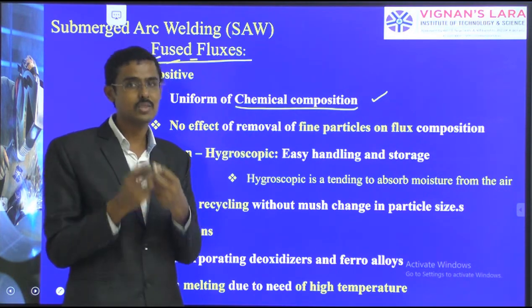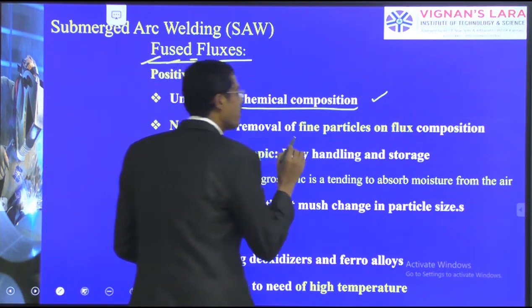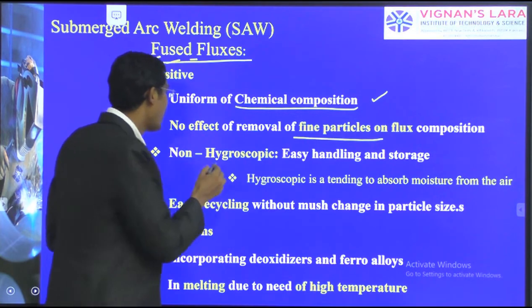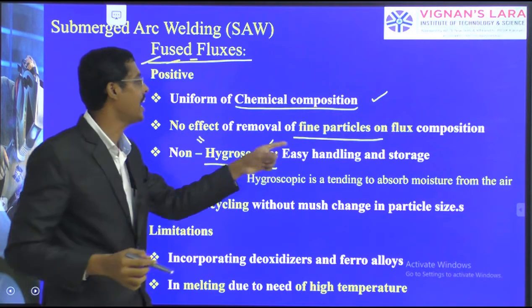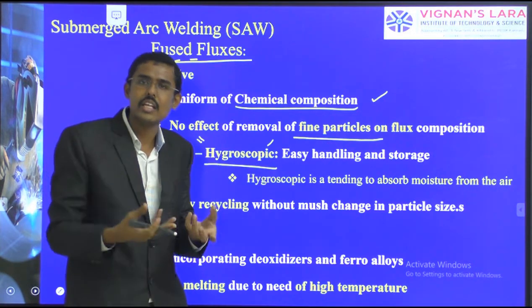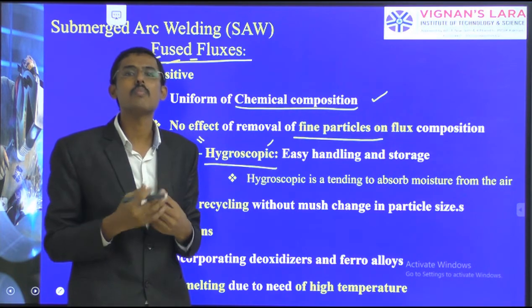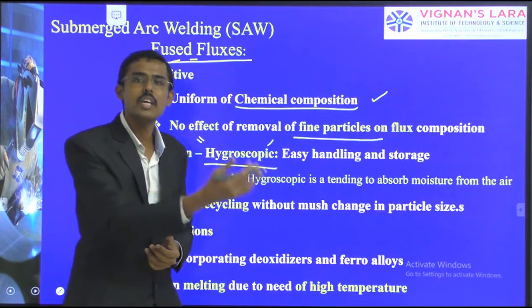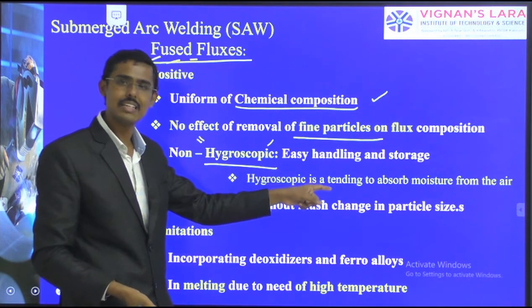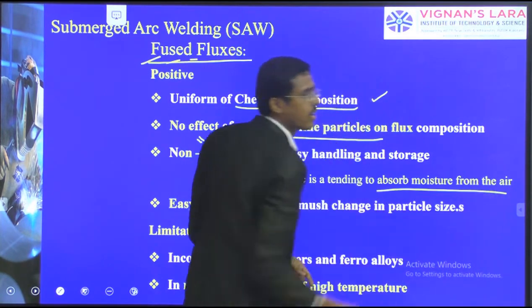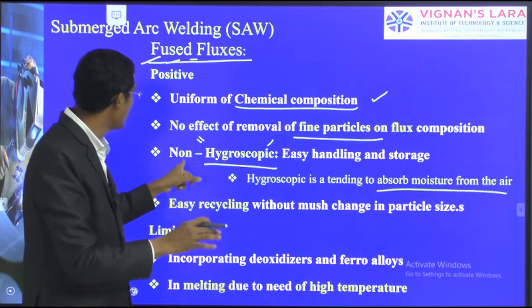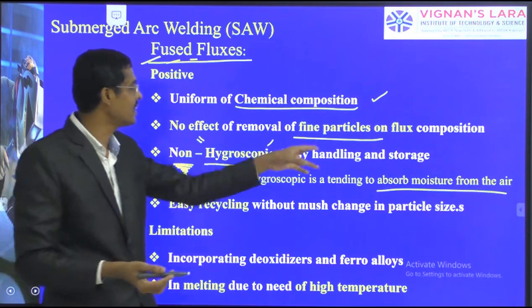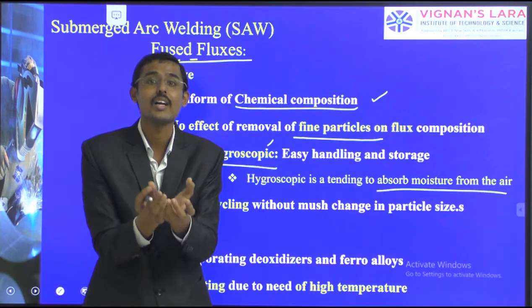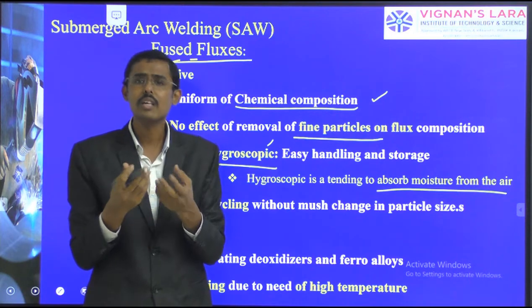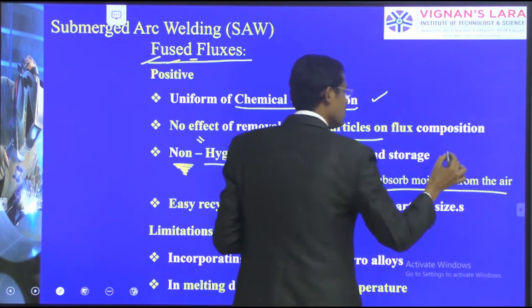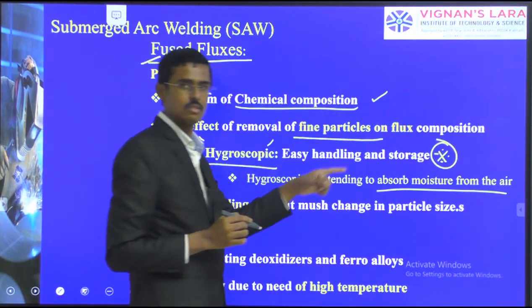Uniform chemical composition is good for the mechanical properties. There is no effect of removal of fine particles on the flux composition. Now, hygroscopic: this word is very important. Handling and storage are easy. After drying, these fused fluxes do not have the tendency to absorb moisture from the environment or air. Hygroscopic is the tendency to absorb moisture from the air, and this tendency is not there, which is why I mentioned non-hygroscopic. If wetness does not come inside, hydrogen will not come in. If hydrogen is there, hydrogen embrittlement will come. Therefore, this is a very important point of fused fluxes.